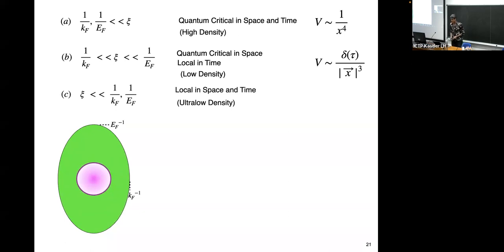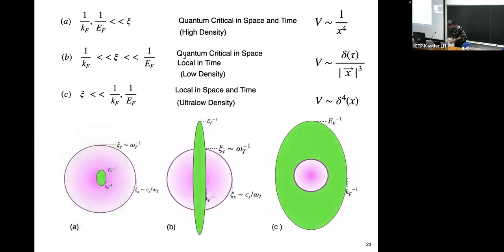Finally, what happens if the correlation length is less than 1/kF and 1/EF? That means that our correlation volume is small compared to what the electrons see. So then we're local in space and time. Just in summary, first we're quantum critical in space and time, but that's for high density. At low density, we're quantum critical in space, but not in time. And then at very low density, we're local in space and time.